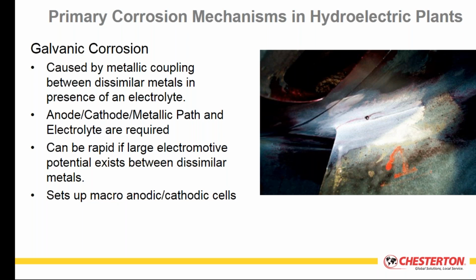When you move to the very active anodic region, you're looking at metals like magnesium or zinc, which are highly reactive. If there is a significant differential between the anodic material and the cathodic material, the rate of corrosion will be quite high and quite fast. If the electromotive potential differential between the two metals is quite close, then you'll have slower corrosion rates, but you will still have corrosion because there is a differential in electromotive potentials.